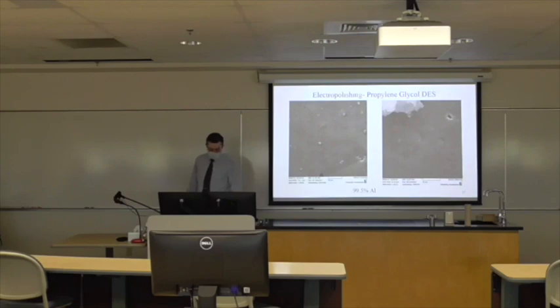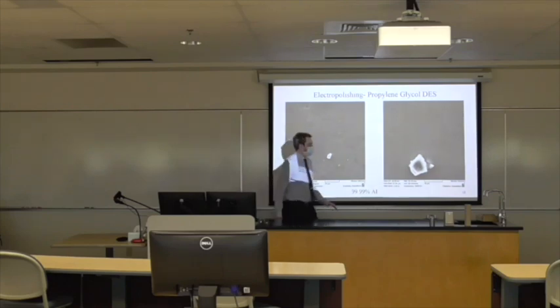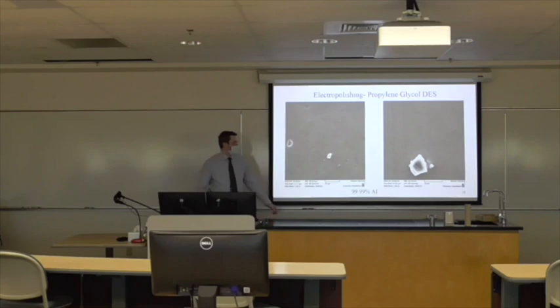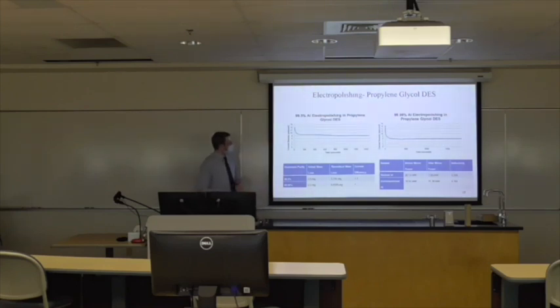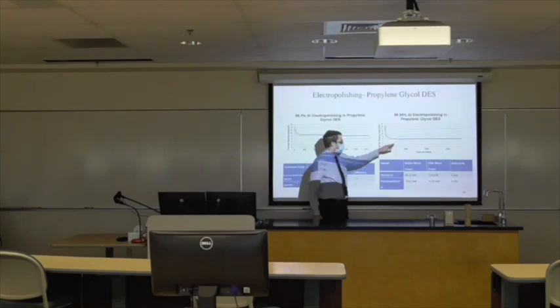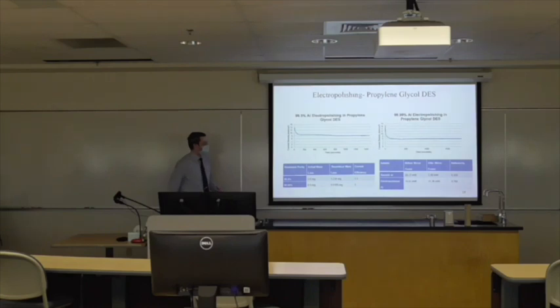Now, with higher purity aluminum, we see that there are even fewer defects for the same amount of time. And at a pretty zoomed in magnification, there are arguably no defects in this area. There's still some if you go looking for them, but the polishing works well. It provides us with a reasonably flat surface for using the aluminum. Now the current density is higher for the 99.5% aluminum that was used in the electropolish with the propylene glycol DES, going to about 8 milliamps per square centimeter. It's a little smoother of a curve, but it goes down to about 6 milliamps per square centimeter with the 99.99% aluminum. Just for information here, the impurities, or the non-aluminum part of the 99.5% aluminum, tend to be iron or silicon. So that is a consideration in why this might be.